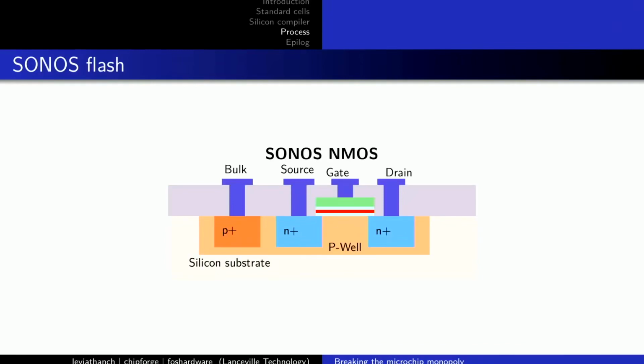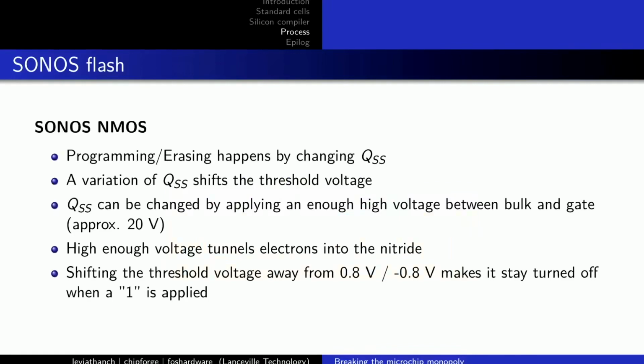So there you have a standard MOS, NMOS in this case, but you have a sandwich. Instead of a normal oxide layer for the gate oxide, you have an oxide, nitride and oxide, and these oxide layers above and below the nitride are called tunnel oxides. The trick is that with a high enough energy, you tunnel electrons through the oxide into the nitride where they are trapped, and then you shift the operation voltage, the threshold of the transistor. When you then put a 1 at it, it doesn't turn on anymore. That's essentially how the most used flash solution besides the normal floating gate works.